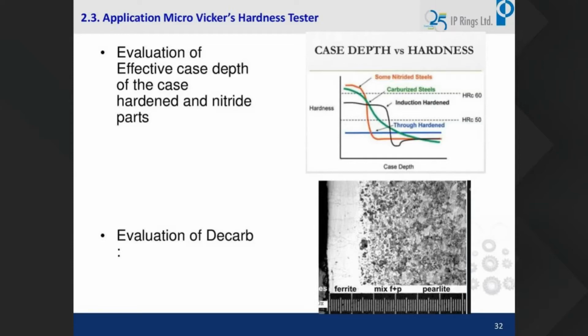What we do is we prepare a mold specimen and we take the indentation from the surface up to a depth, and there is a cutoff for different parts. For case hardened parts it is 50 HRC, whereas for nitrided parts it is somewhere around 700 HV. That is the cutoff. So we calculate to what extent the effective case depth is with the help of this micro Vickers tester. And also, in the standard evaluation of decarb, you can just section the product, prepare the metallographic specimen and check the microstructure. With the help of microstructure, we will be able to evaluate the decarb.